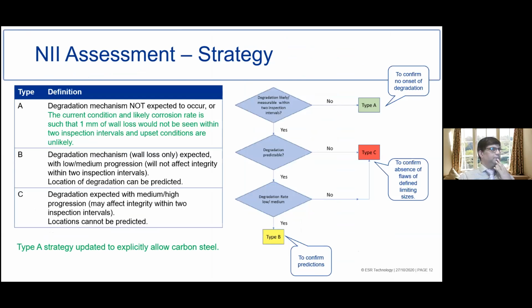If you determine that a vessel is suitable for NII, there are 3 different strategies you can take. There's type A, where the aim is to confirm that there's no onset of degradation, which would be a sampling inspection. A type B, which is to confirm your predictions, which would also be a sampling inspection, but at a higher coverage. And a type C, where you're confirming absence of flaws of a particular defined limiting size, and that's like 100% coverage. So changes that are in the recommended practice now, the flowchart on the right there is new, just to help people who are perhaps more visual in the way they read things.